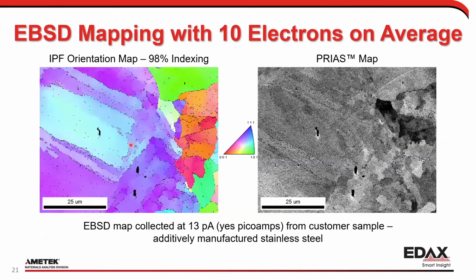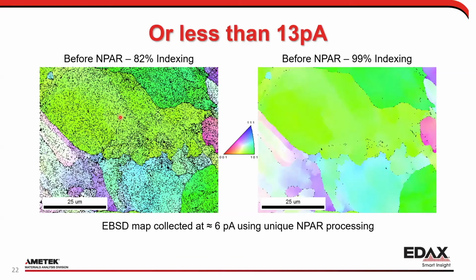So I can see that this is going to be pretty good for beam sensitive materials, doing very fine scale work. 13 picoamps is pretty tiny, but that's 10 electrons per pixel. I can do less. This right here is actually at 6 picoamps. On the left-hand side, you can see it's having a little bit of problems. There is some data being dropped out, but it's also doing a very good job with the data it does have. Running that through NPAR basically makes a very okay data set into essentially a perfect data set. Again, this is at 6 picoamps.